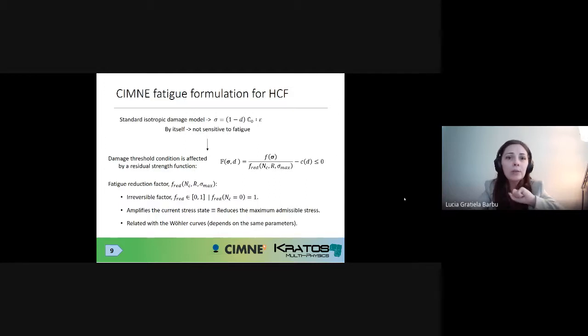So a little bit more detail about this reduction function. Basically, it's an irreversible factor. You cannot go back. You cannot recuperate it. It starts at the beginning of a simulation when you have a virgin material with a reduction coefficient of 1. And as you advance and you apply a number of cycles, then you progressively lower this coefficient. Basically, the effect it has when you include it inside this damage threshold condition is that it either amplifies the current stress state until you reach the threshold and you go into the nonlinear domain, or you can see it as absolutely equivalent to reducing the maximum admissible stress inside your material. And the expression of this reduction function is related 100% with the Wöhler curves, with the stress-number of cycles curves. What do I mean by related? I mean, it depends on the same material parameters that you have to calibrate.